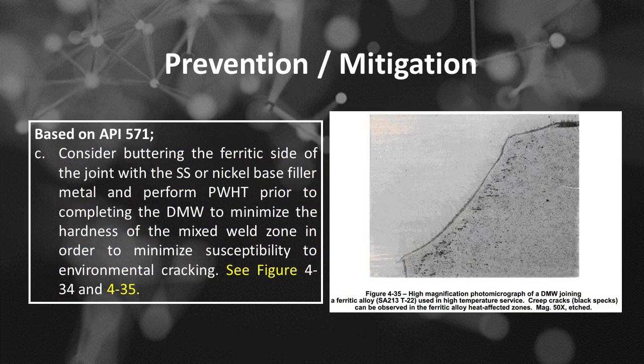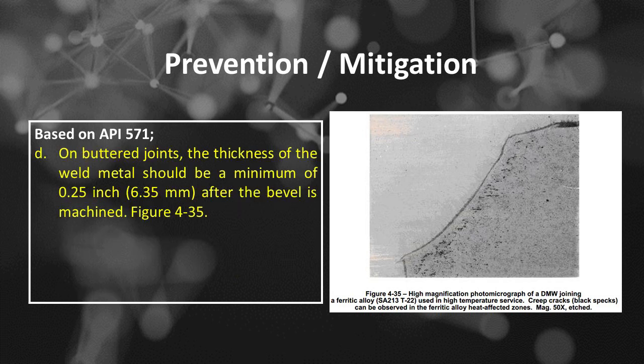Figure 4.35. High magnification photomicrograph of a DMW joining a ferritic alloy, SA213T22, used in high temperature service. Creep cracks, black specks, can be observed in the ferritic alloy heat affected zones. Mag 50X, etched. The fourth is on buttered joints. The thickness of the weld metal should be a minimum of 0.25 inch, 6.35 mm, after the bevel is machined.